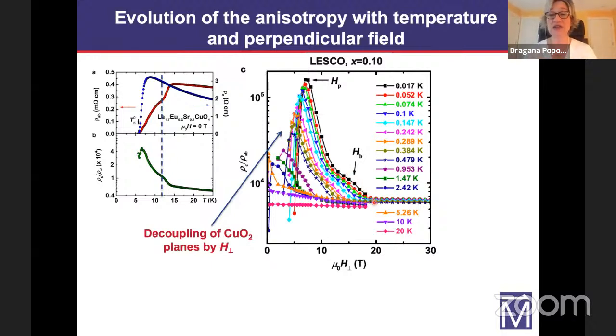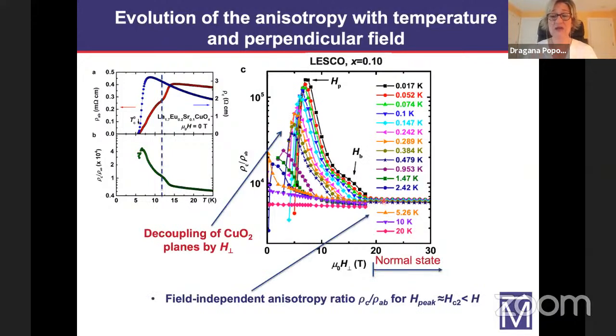And eventually at high enough field, the anisotropy no longer depends on the field, and it's comparable to the value we had at high temperature. So this is what you expect in the normal state. This happens in this material at fields above 20 Tesla, which is exactly the upper critical field that we had identified based on those other measurements that I showed you earlier. So this supports our conclusion that this is the upper critical field.